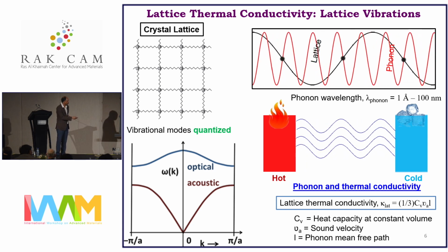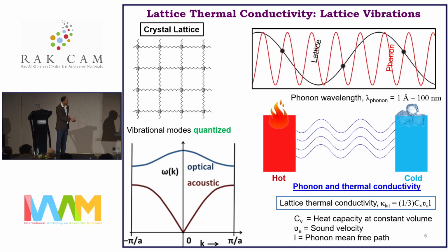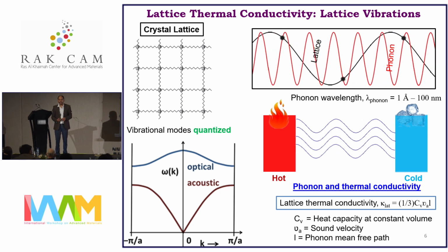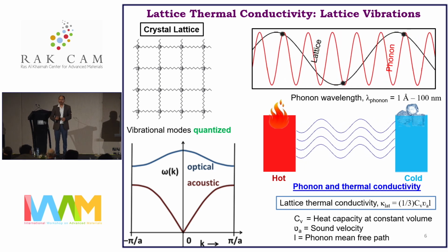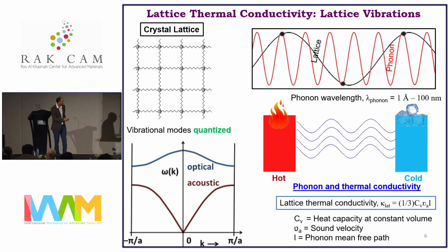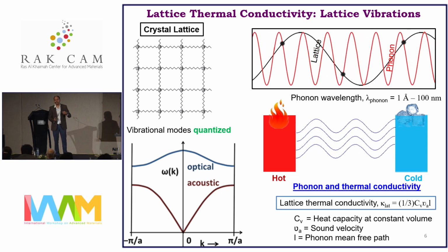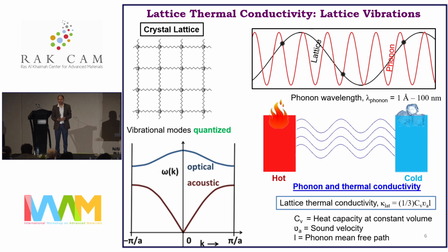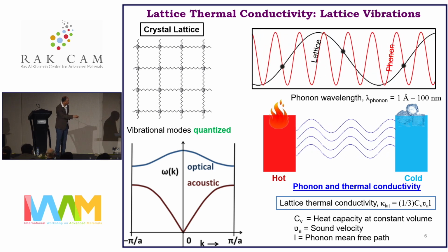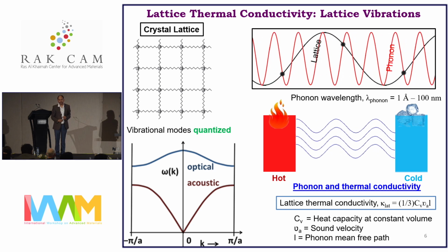You can see there are two types of phonons, optical phonons and acoustic phonons, and acoustic phonons are generally responsible for carrying the heat in a solid. In a simple one-dimensional lattice, when all atoms vibrate in the same direction, it generates the acoustic phonon. When the atoms vibrate in different directions, that generates the optical phonon, which can be tracked by spectroscopic techniques such as Raman, IR, or terahertz. So how do we slow down this acoustic phonon to decrease the thermal conductivity?